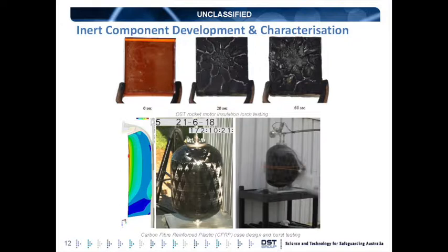obviously very important for space access, how it bonds to the propellant, how it tolerates extreme environments and how it responds to ablation and erosion rate, and how it can tolerate whole of system changes such as thermal expansion. We test this using torch tests, material testing, bond strength testing as well to ensure that there's sufficient stress relief and ensure that we have the required manufacturing tolerance, the strength, and also, most importantly, erosion resistance of the same.